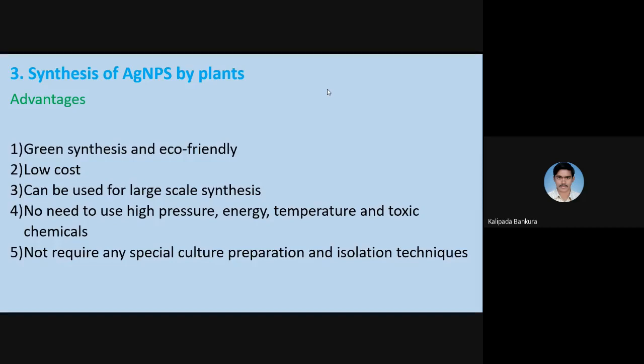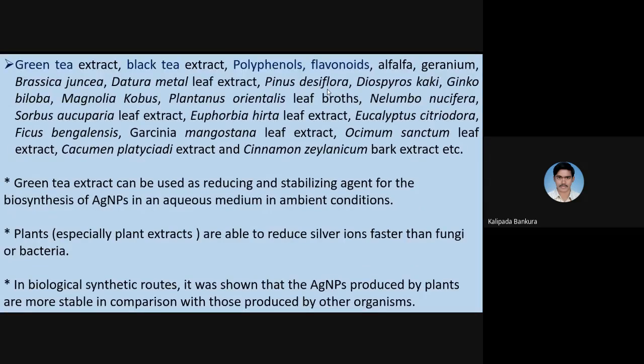Reported plants are green tea plant extract, black tea extract, alfalfa, geranium, etc. Leaf extracts are used to synthesize silver nanoparticles. Green tea extract can be used as a reducing and stabilizing agent for the biosynthesis of silver nanoparticles in aqueous medium in ambient conditions. Plants are able to reduce silver ions faster than fungi or bacteria. In biological synthetic routes, it is shown that the Ag nanoparticles produced by plants are more stable compared to the other chemical or organism methods.